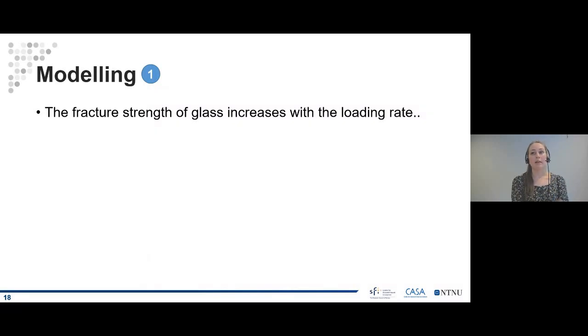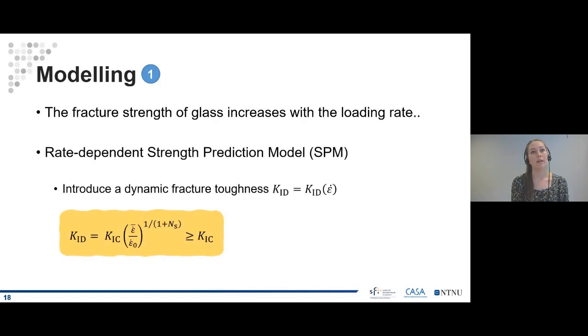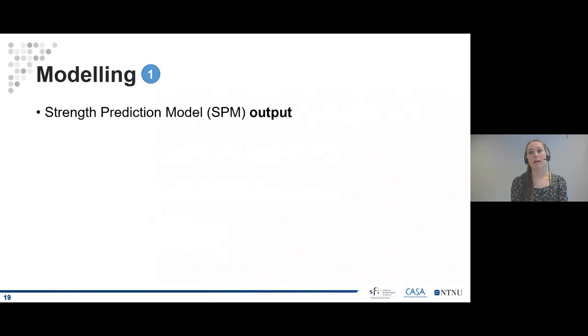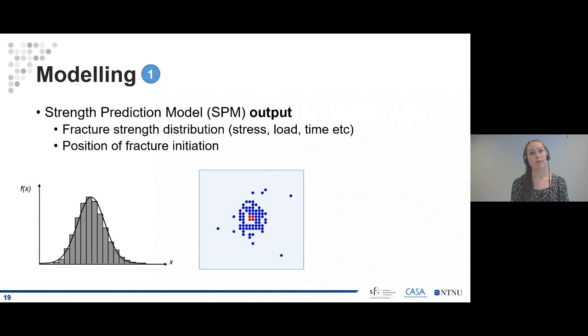I mentioned before that the fracture strength of glass changes with the loading rate. So we also wanted to include this effect in the strength prediction model. To include rate dependency, we chose to introduce a dynamic fracture toughness, which depends on the strain rate. And this is shown in the yellow box. All right, so the output that we can get from this SPM model is the fracture strength distribution in terms of, for example, the stress, the fracture time, or the load. And we can also get a map of the position of fracture initiation.